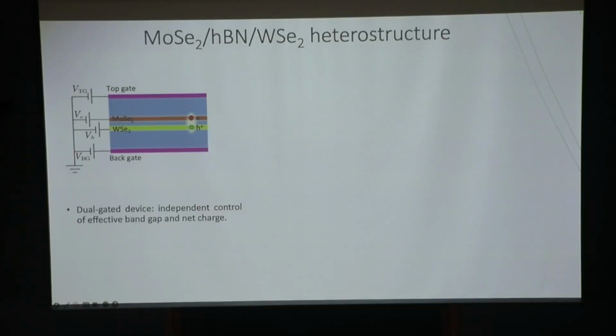Here I again show an illustration of a typical structure. The key components are MoSe2 and WSe2, two semiconductor layers that can host the electrons and holes. They have a boron nitride dielectric in between. At the same time, we also have a top and bottom gate, so this is a dual gate. And each of these layers can be controlled electrically. This electrical knob is extremely important because it allows us to tune in situ the effective band structure and the doping, and then explore different phase diagrams.